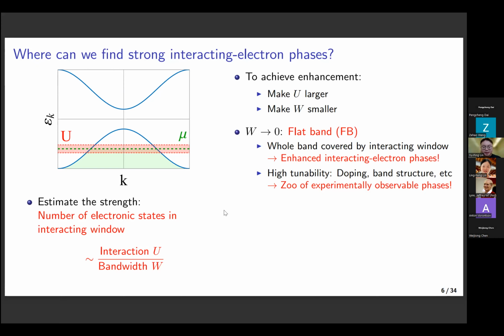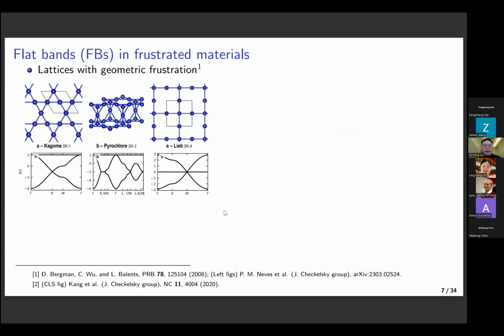So now we know that the flat band is good. And the question is, where can we find flat bands in materials or experimentally accessible systems? There have been a lot of flat band systems that have been proposed, like moiré systems, for example. But today I'm going to focus on another family of flat band materials, which is frustrated systems. It has been known that if we have frustration on the lattices, for example, in kagome, pyrochlore or Lieb lattices, then we can have a flat band in the band structure. For example, in the kagome lattice, we have the flat band at the top of the band structure. And for pyrochlore, we have doubly degenerate flat bands. And for a Lieb lattice, we have a middle flat band.